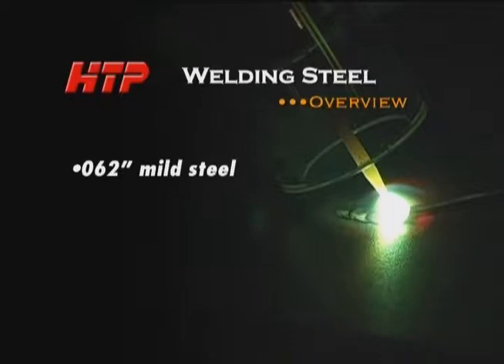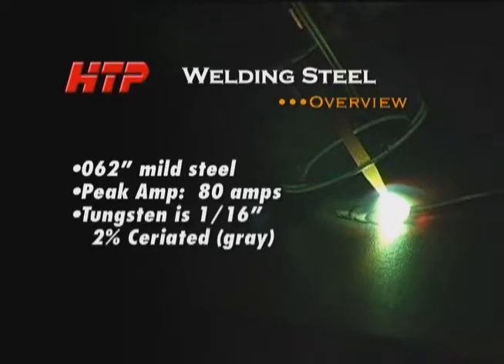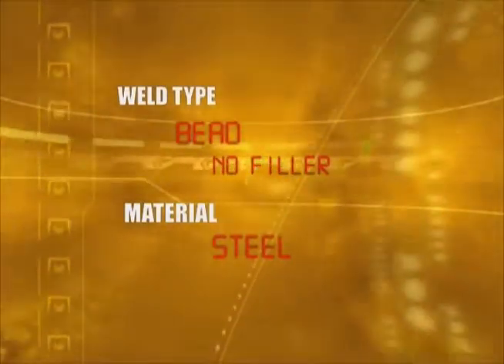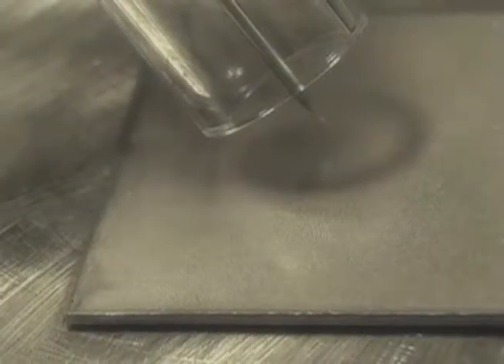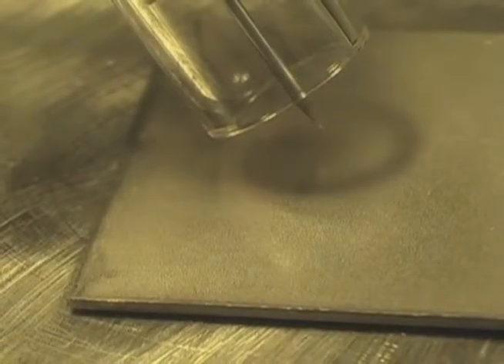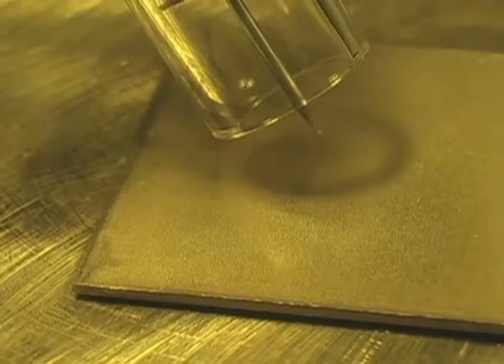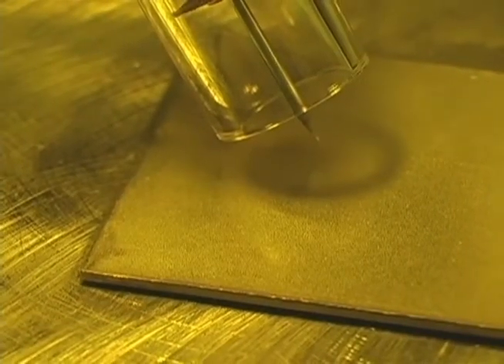We will start by running a bead on 062 mild steel. Peak amperage is set to 80 amps, and we will probably be welding at 60 amps. Tungsten is 1/16 2% Ceriated. Before you can even think about joining two pieces of metal together, you want to become proficient in just being able to run a bead, without even putting filler metal in. The object of this exercise is to keep the tungsten between 1/8 and 3/16 of an inch off the work and move it in a very constant motion.